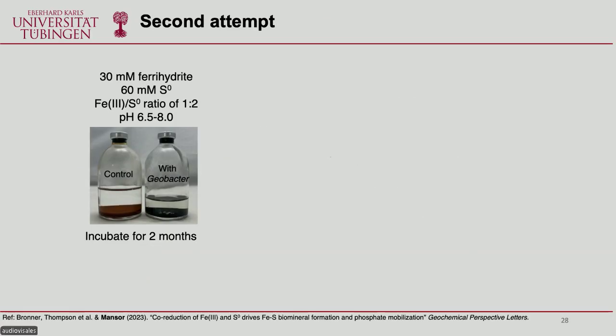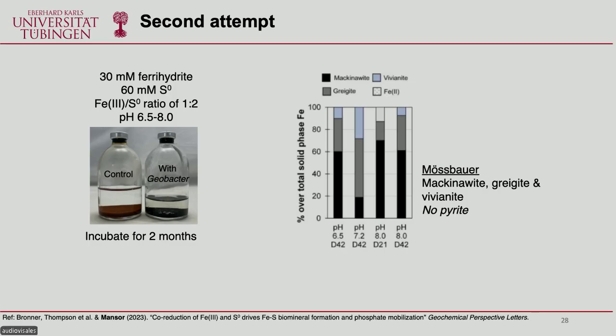Let's try it. So we have ferrihydrite as a source of iron, and sulfur. We try an iron-to-sulfur ratio of 1:2 at circumneutral pH. And you can see that in the control, we have this brown coloration, which is typical of iron(III) mineral. And then after 2 months, we have these black mineral precipitates. So then we analyzed this using Mössbauer spectroscopy, which is a way to identify the mineralogy, and no pyrite. After 2 months or so, we're still stuck at mackinawite and greigite, these intermediate iron-sulfur minerals. And also, interestingly, we formed some vivianite.